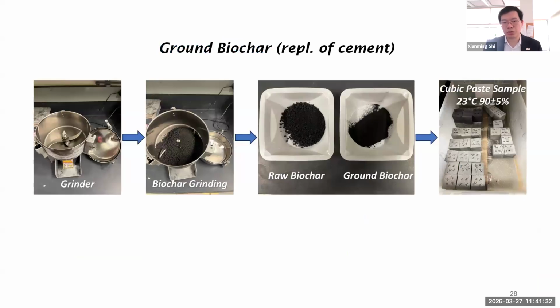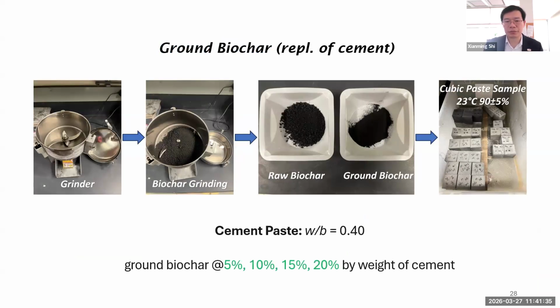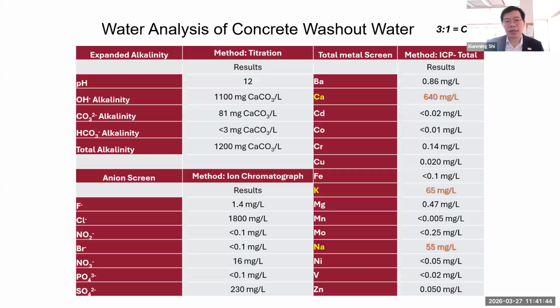So again, the same as usual, with grinding, we get ground biochar to replace 5, 10, 15, 20% of cement in the concrete. Well, actually, in this case, we start from cement paste. Just for those who are curious, what's in the concrete washout water? Again, pH 12.0, and there are all kinds of trace elements. There's some calcium, some potassium, some sodium in it, which is what we need to enable that precipitation of carbonate on the surface of biochar.